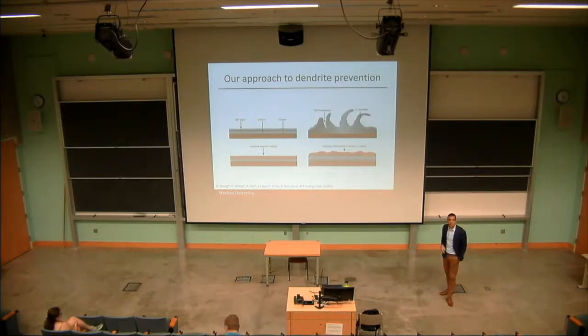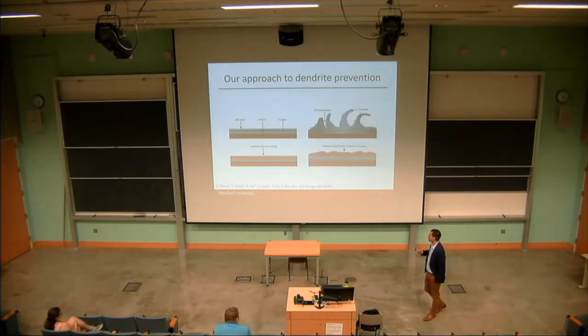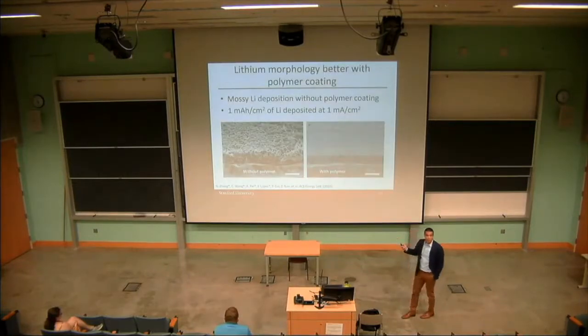So we took that self-healing polymer that I showed before in previous slides, and we coated it on the lithium metal electrode here. And the idea is that if we have this artificial SEI, or this polymer coating that's present, and it has very, very soft, very, very flowable mechanical properties, any sort of cracks or pinholes that form in the SEI will be healed over time as the polymer flows into those cracks. And then hopefully we'll have very dense, very uniform deposits under this adaptive polymer coating. And that's what we see.